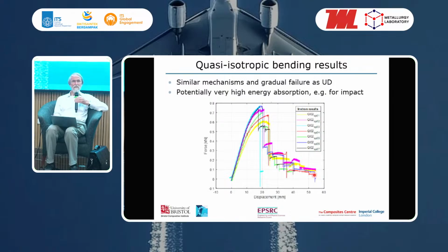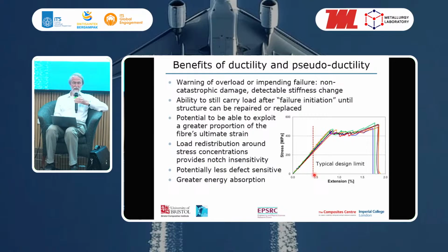So that's a summary of what we found on the behavior of these materials in tension, compression, and bending. Just a few comments on the benefits of ductility and pseudoductility. This pseudoductility gives a warning that the specimen has been overloaded and might be close to impending failure. We get non-catastrophic damage, but we get a detectable stiffness change. And in fact, that stiffness change can be seen visually in some cases. If we have a carbon glass, we can see it visually as well as measuring it by the change in stiffness. And recently, we've been doing some work on looking at the effect of electrical resistance. We can also detect the damage by a change in electrical resistance.